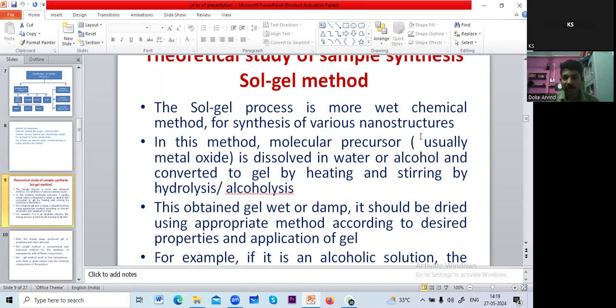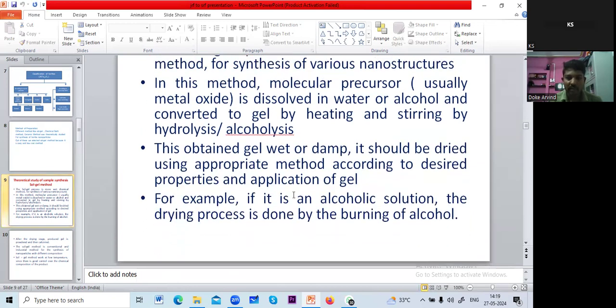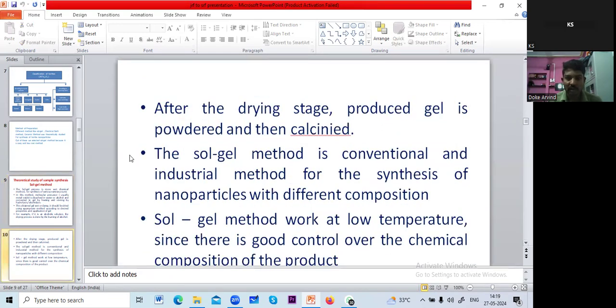In this method, molecular precursor, usually metal oxide, is dissolved in water or alcohol and converted to gel by heating and stirring by hydrolysis or alcoholysis. This obtained gel, wet or damp, should be dried using an appropriate method according to desired properties and application. For example, if it is an alcoholic solution, the drying process is done by burning of alcohol. After the drying stage, the produced gel is powdered and then calcined.